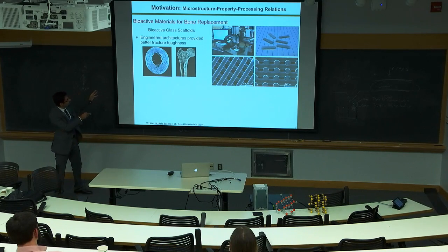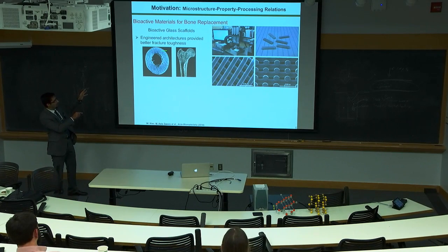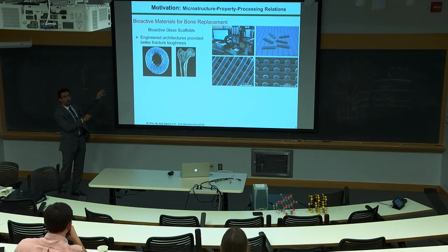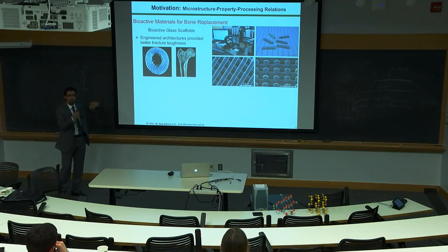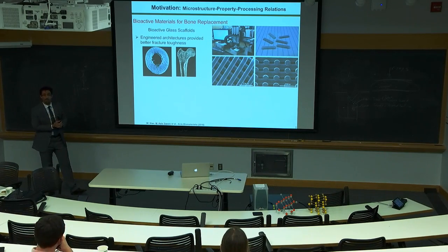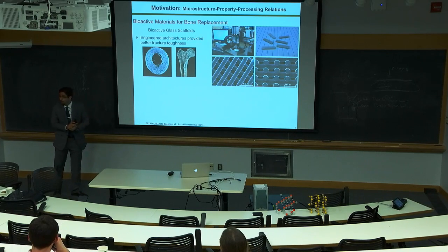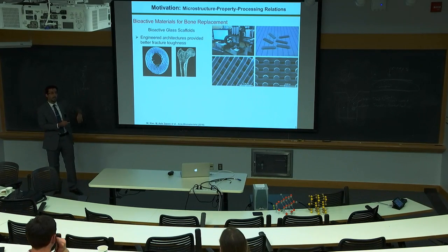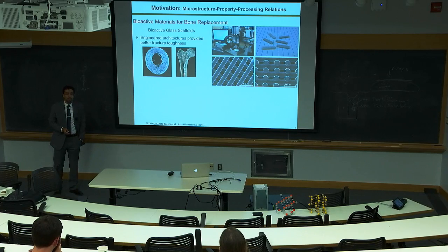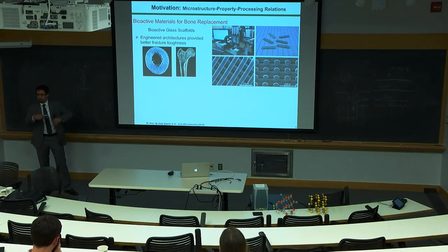If you look at a cross-section of a long bone, at the surfaces you have high density. As you go inside, you get more porosity. And in the middle you have a very big porosity. So based on this, we wanted to design an architecture that increases the flexural strength, or bending strength.